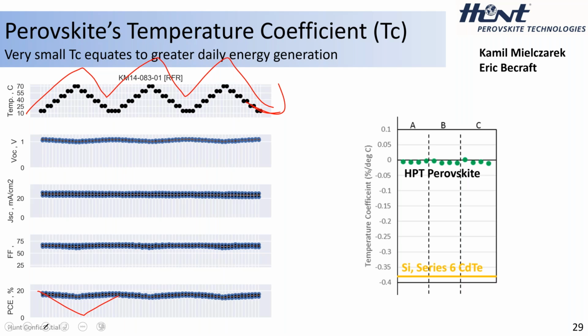In our case, we see the requisite drop in voltage as expected by physics. There's a small drop in our fill factor, again, also a little small drop, but our current density is completely flat. So overall, we do have a negative thermal coefficient, but a small one, about an order of magnitude less than that of silicon. Not quite, maybe 8x, 7x, 9x, somewhere in that range, but it's quite robust.